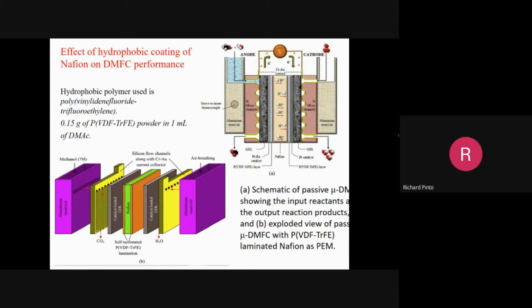If the methanol, without breaking into carbon dioxide and H plus, penetrates the membrane and goes to the cathode side, then we have a short circuit effect. So the power density drops. So we need to reduce the membrane permeability. One way of reducing permeability is coating a thin layer of another material.